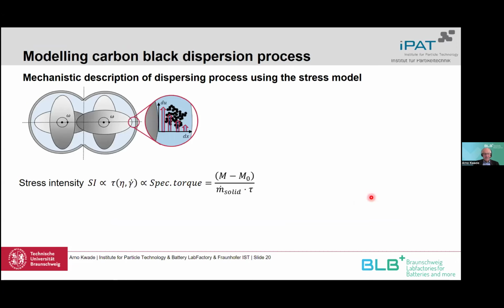Now, what happens in the machine, if you look into the screw design, is that we stress the particles due to shear inside the suspension, and we can describe that by the so-called stress intensity, which is nothing less than the shear stress inside our extrusion machine. As a measure of that, we can use the torque or the specific torque of the machine. Besides that, we have to see how often such particles are stressed, at least in the volumes where we have really high stress intensity, especially where the two screws come together. If we multiply both, we have a measure for the specific energy input into the process.